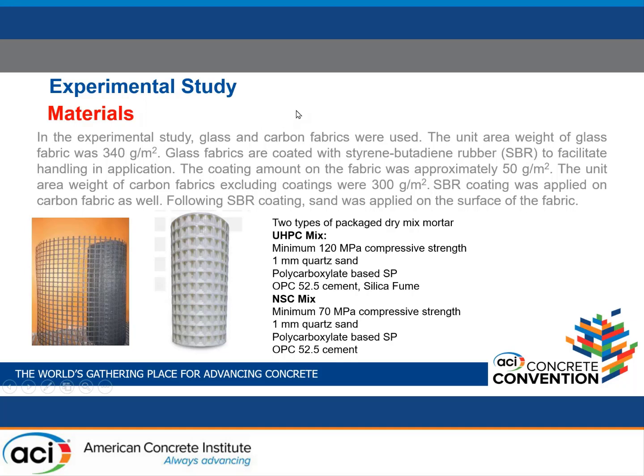The details of the experimental study. In the experimental study, glass and carbon fabrics were used. The unit area weight of glass fabric was 340 grams per square meter. Glass fabrics are coated with styrene butadiene rubber to facilitate handling and application. The coating amount on the fabric was approximately 50 grams per square meter. The unit area weight of carbon fabrics, excluding coating, was 300 grams per square meter. Again, a coating was applied on carbon fabric as well, and sand was applied on the surface of the carbon fabric to increase the bonding properties.